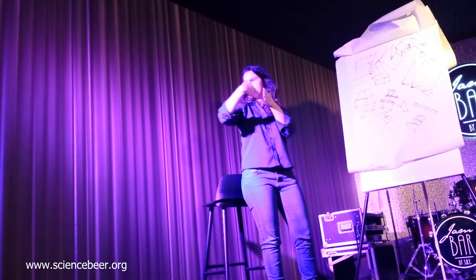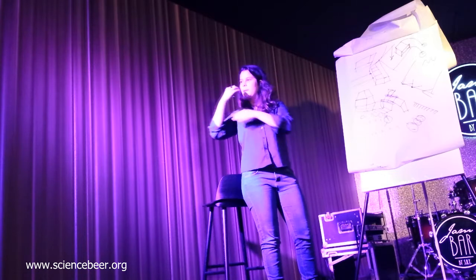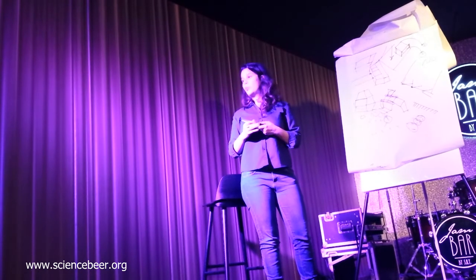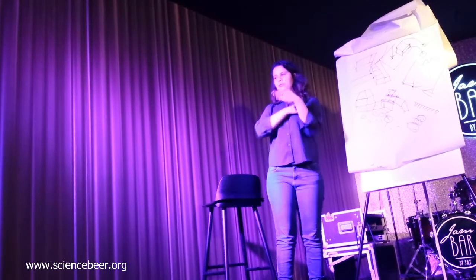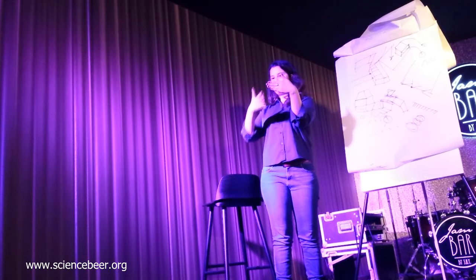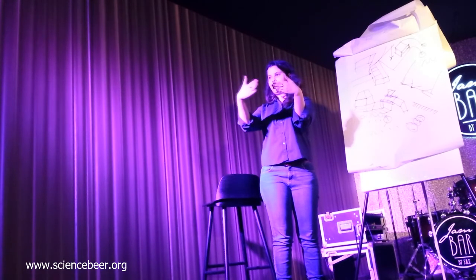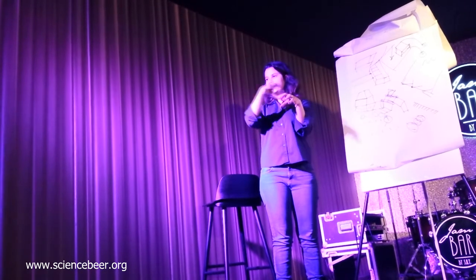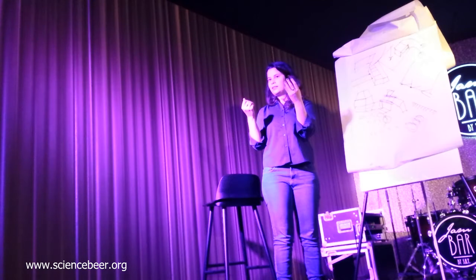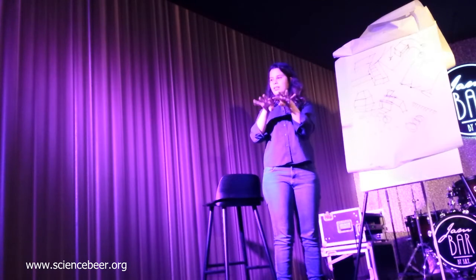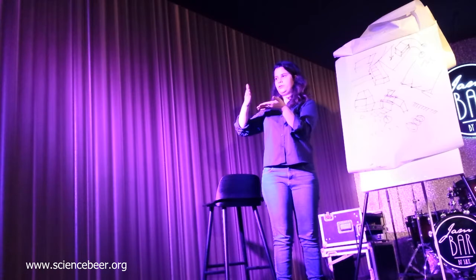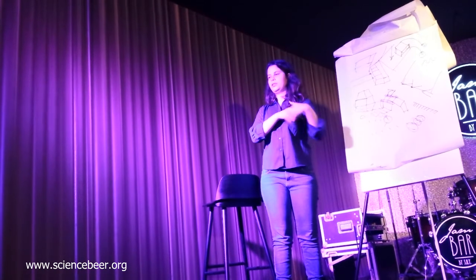Depending, they grow in different ways. But in the end, they are not separated anymore. No, they're connected. Sometimes you get a few millimeters grain in this direction, and then you get a boundary here. But these films are all interconnected. Because they're very thin, they don't crack. If you go thicker, you can get these cracks and disjointed films, but you can control with these parameters that they're very continuous.